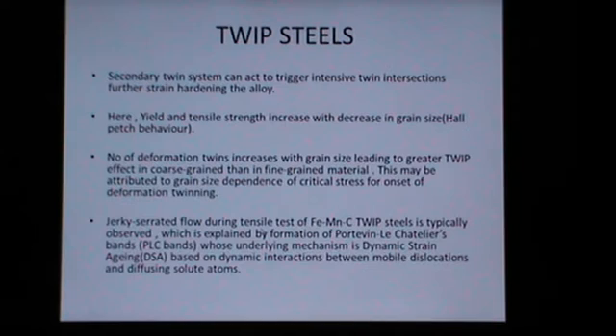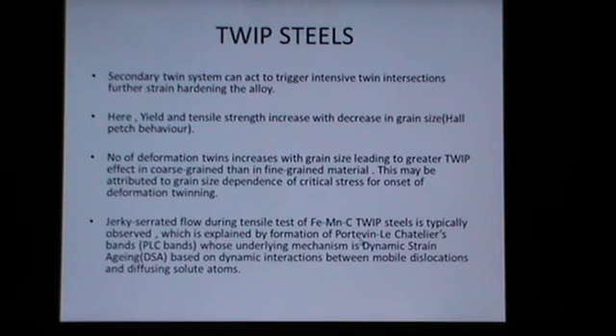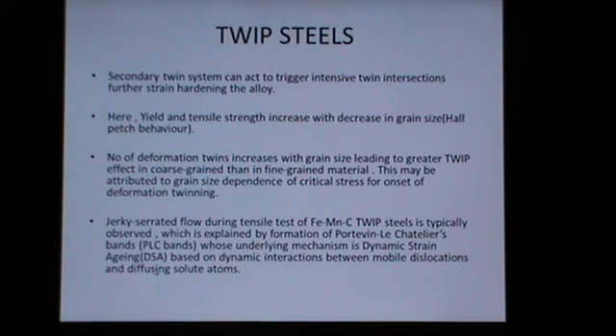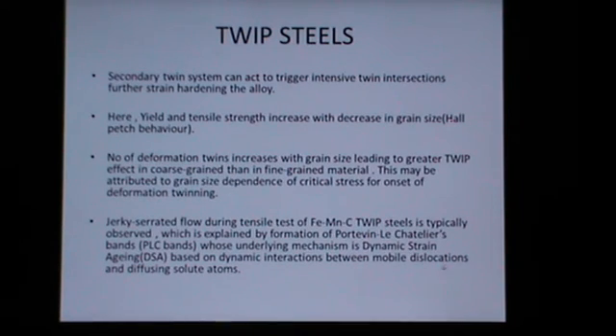Jerky, serrated flow during tensile testing of iron-manganese-carbon TWIP Steels is typically observed, which is explained by the formation of Portevin-Le Chatelier bands, or PLC bands, whose underlying mechanism is dynamic strain aging, or DSA, which is based on dynamic interactions between mobile dislocations and diffusing solute atoms.